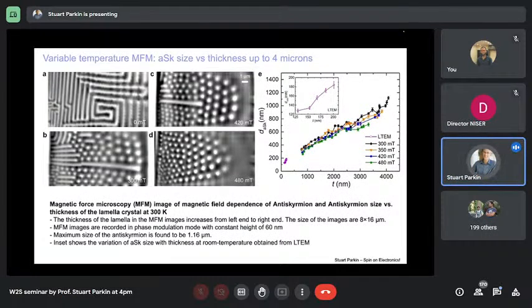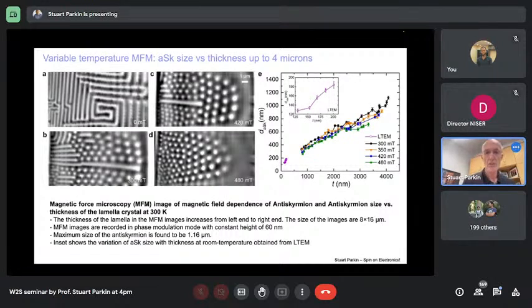So this is what makes these anti-skyrmions so interesting. A very complex magnetic texture, which is derived from the symmetry of the Dzyaloshinskii-Moriya interaction, which is coupled to the symmetry of the crystal lattice. And this was the first observation. Now this has been seen in the same material. This is, by the way, a Heusler compound, by Yoshinori Tokura's group. They made exactly the same crystals that we had used, and they basically discovered the same result.